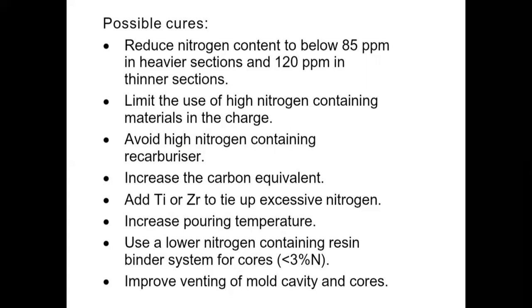Now we go to the remedies — the possible cures. First, reduce nitrogen content to below 85 ppm in heavier sections and 120 ppm in thinner sections. Limit the use of high nitrogen-containing materials in the charge, especially CPC coke in cast iron as a carburizer.